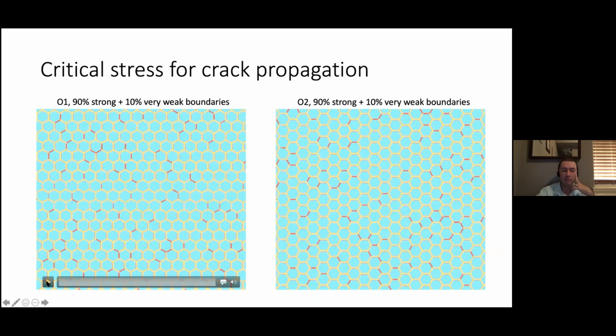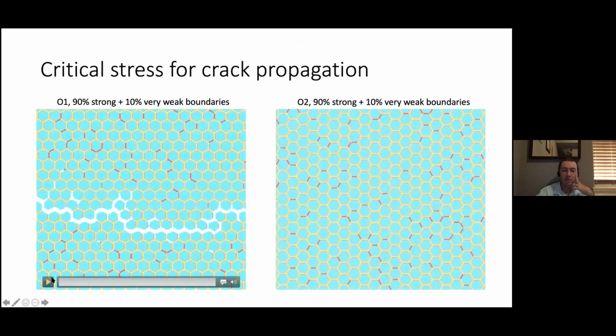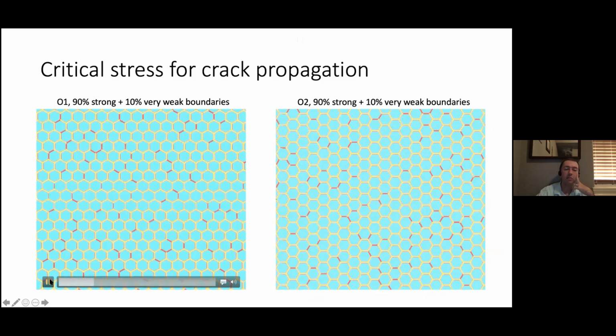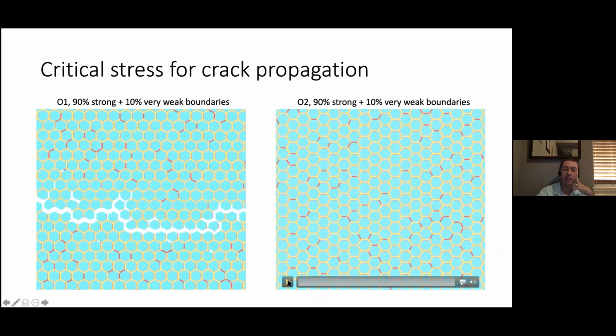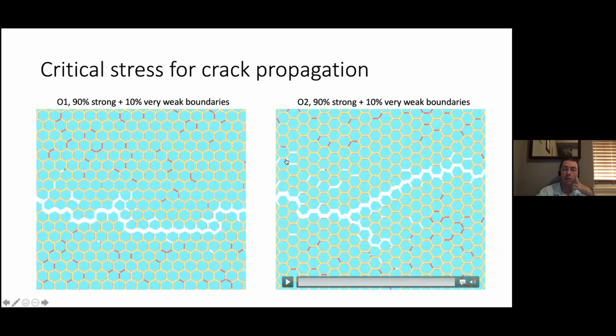So this is just a movie of one of those cracks running through. And you can see that it starts out barely moving along, and then suddenly it shoots across as soon as it reaches that critical stress intensity. And if you look closely, you can actually see the daughter cracks and the branching events occurring as this crack tries to propagate from left to right. Same thing here, this is the other orientation. You see a little bit more in the way of daughter crack nucleation. You see a big branch here, and then basically this other branch with additional daughter cracks moving off to the side.